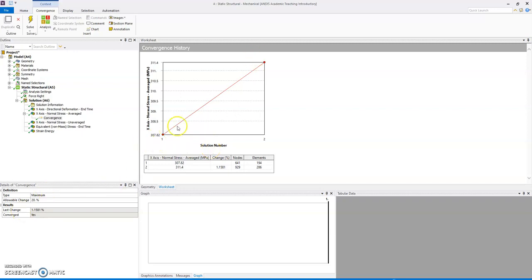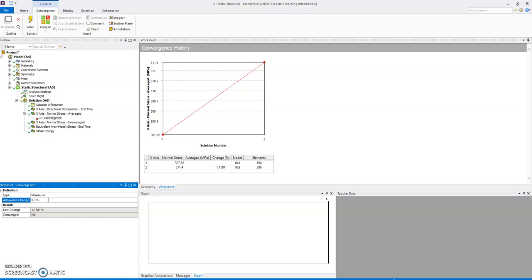When you do a calculation, your accuracy is going to be limited by the built-in accuracy of the data you are using. For instance, a Young's modulus is accurate to what? Plus minus a few gigapascals, that's usually one or two, it depends. Rule of thumb is around five percent from experimental data, which is, there are exceptions of course. Things can be done much more accurately, but be aware that your accuracy is not what you think it is. It's not because the computer gives you a lot of decimal points, but the real accuracy is way worse than that. That being said, I'm not happy with that, I want to go further.